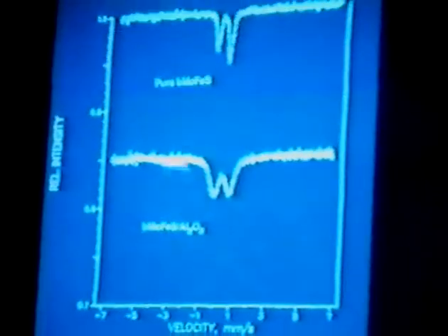We also use Mössbauer spectroscopy to try and follow the genesis of the materials, and found that for the pure molybdenum iron sulfide, the mixed metal cluster, we can ascribe the iron as being in a zero valent state. Once we put this on the surface, unlike the IR results, we notice that there's a shift in the isomer shift.